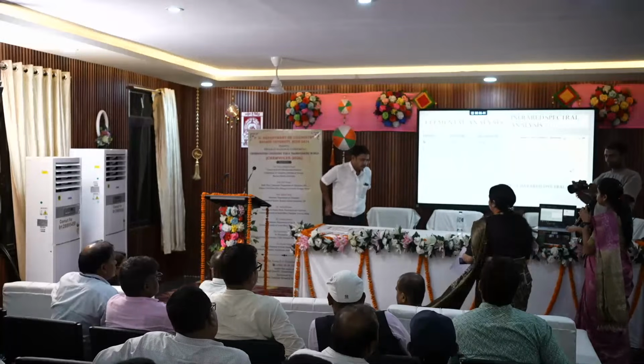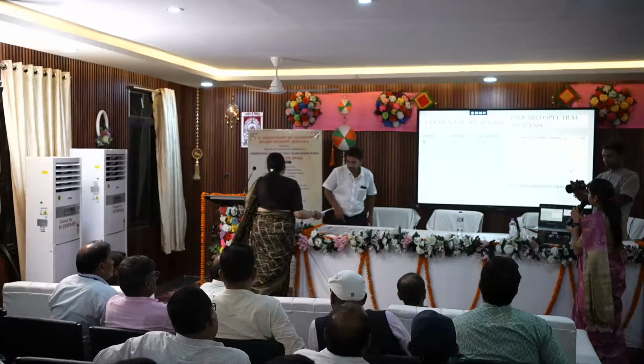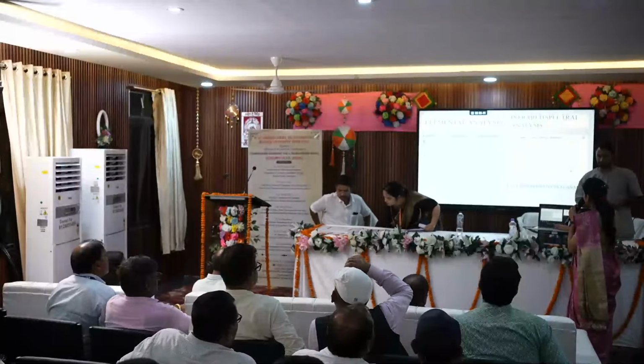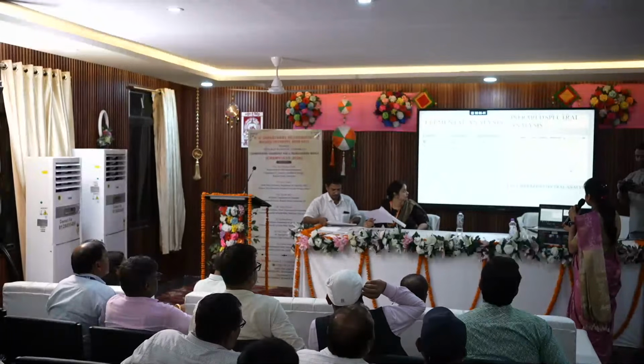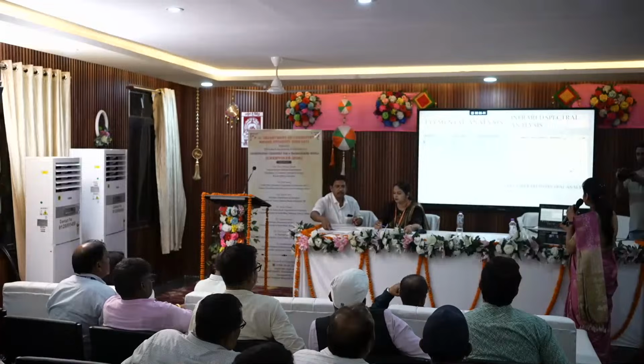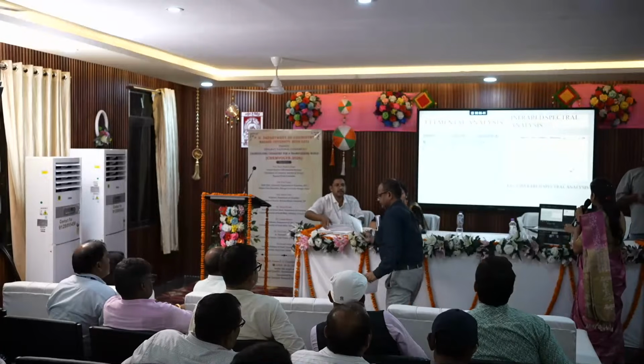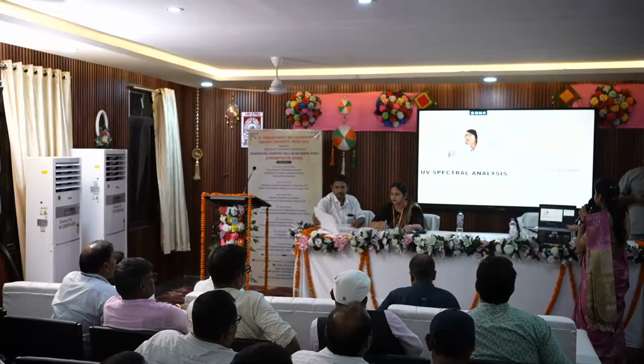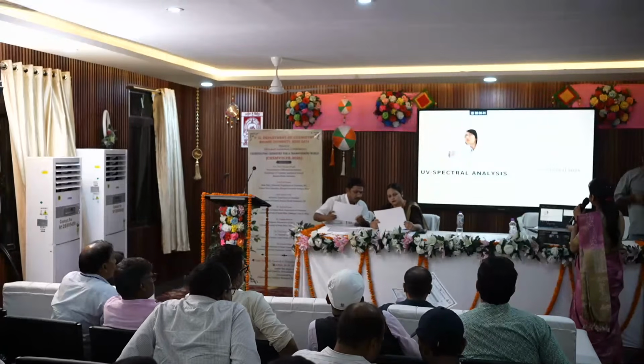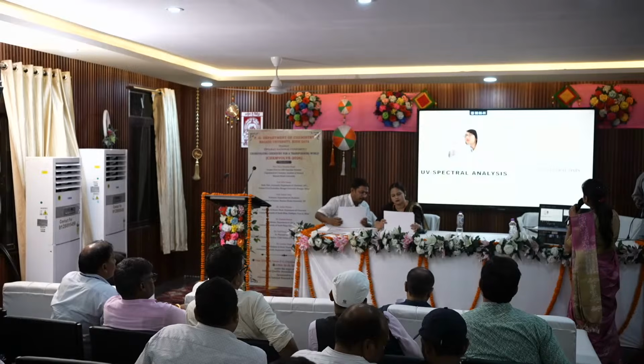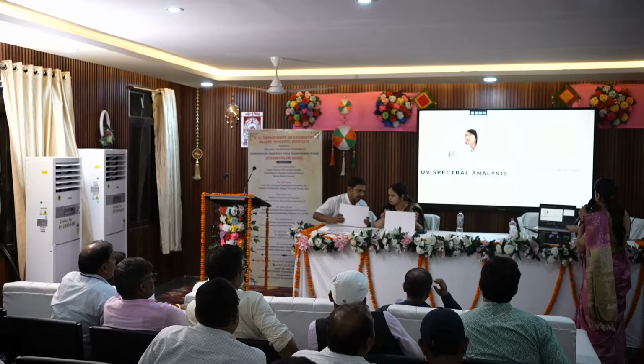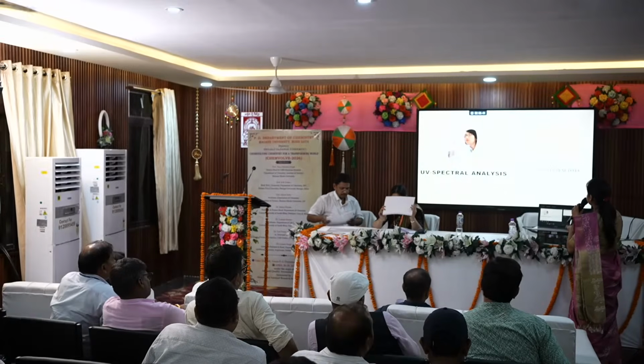This is the elemental analysis of biguanide sulfate, in which carbon content and nitrogen content are found as 10.11 and 29.90 respectively. This is the IR spectral analysis, in which the peak around 3400 cm⁻¹ shows the NH stretching, while the peak around 1500 shows the C=N stretching, which corresponds to the guanidine molecule. The stretching around 1100 shows the sulfate stretching. This is the UV spectral data, which shows the π to π* transition, the intense peak, and the weaker peak around the n to π* transition. So this was for the biguanide sulfate ligand.